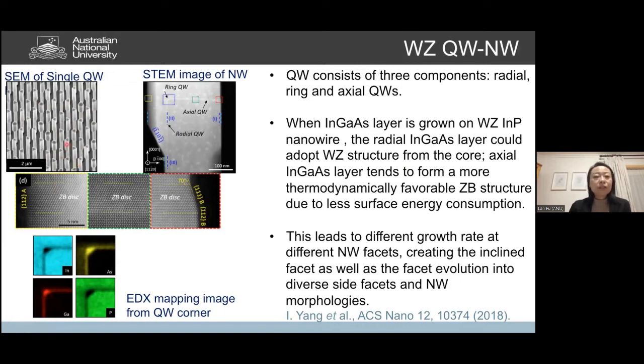And then we actually tried TEM, and we found that indeed, even though it looks very non-uniform and very strange, we have actual quantum wells formed inside the nanowire. And the quantum well has three different components. We have this axial component, this radial component, and the ring component, and a corner component, which show different compositions in the EDX mapping. So we basically have three different quantum wells inside. And if you do a more careful analysis of the structure, we found that it has a quite complicated structure, like we have a mixed zinc blende and wurtzite segment inside the nanowire at different locations.